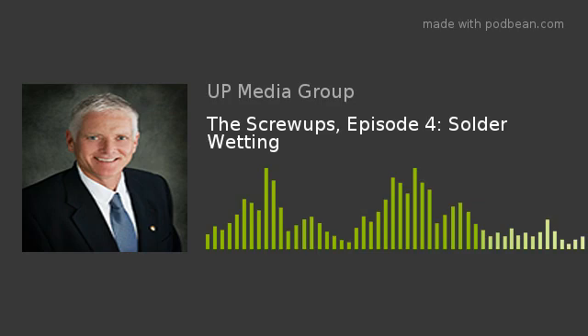So there's the non-wet condition, and I'll describe that as meaning the component wasn't solderable, or the solder was inadequate to solder the substrates. So the flux selection, for example, wasn't aggressive enough to wet to whatever it is that we want to wet to. I got a call this week from somebody who wanted to solder to plate aluminum. Well, plate aluminum requires basically straight hydrochloric acid in order to remove the aluminum oxides and have a chance of even wetting the surface. So to submit a solder paste sample of no clean, it would just turn into a ball and wouldn't solder at all. So that would be a non-wet situation where there just isn't the right product or the right flux for the given application. And then there's a de-wetting condition.